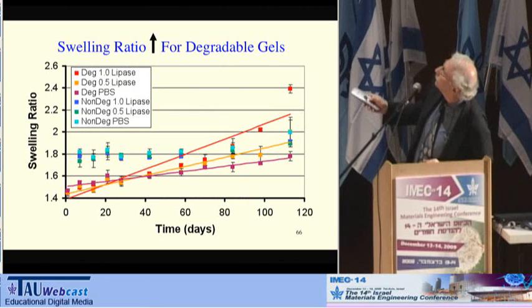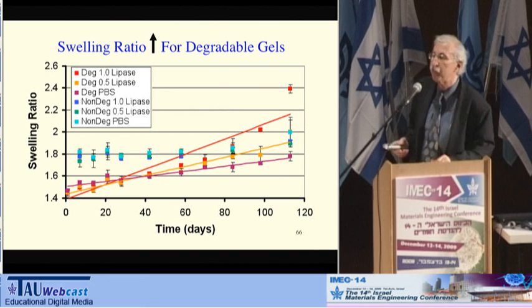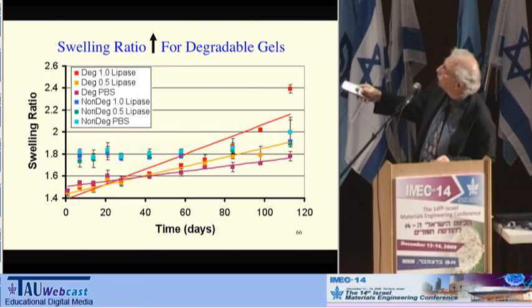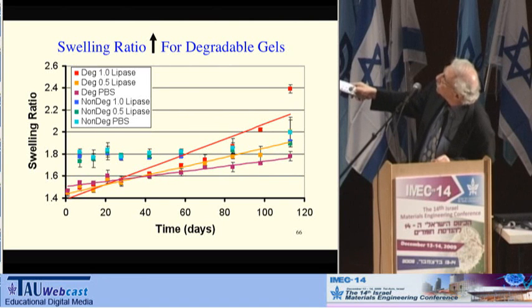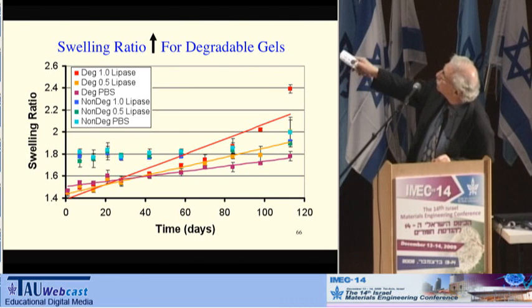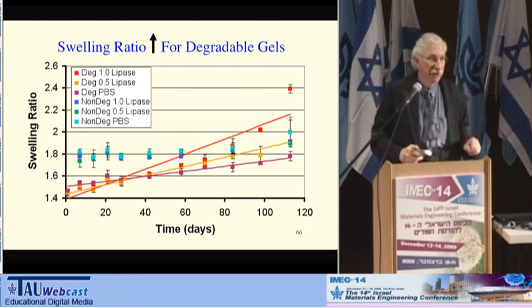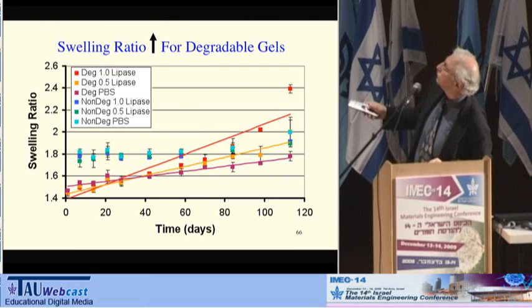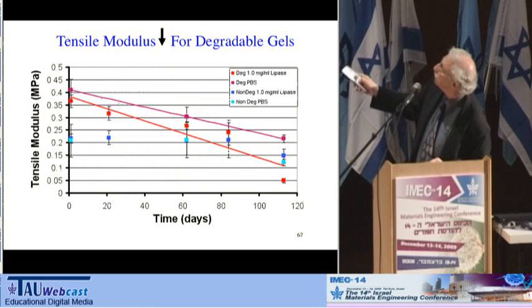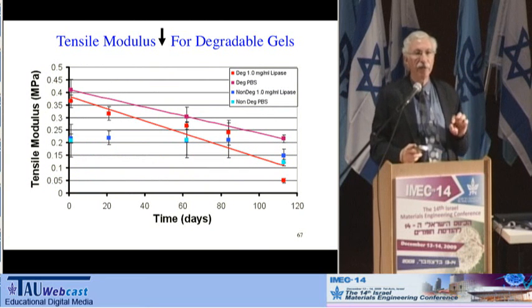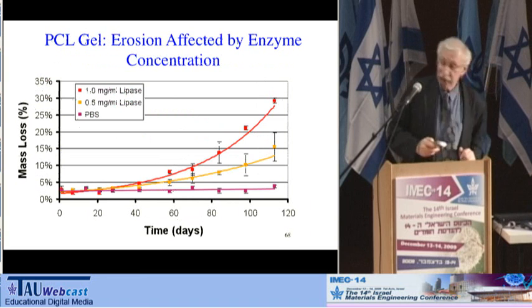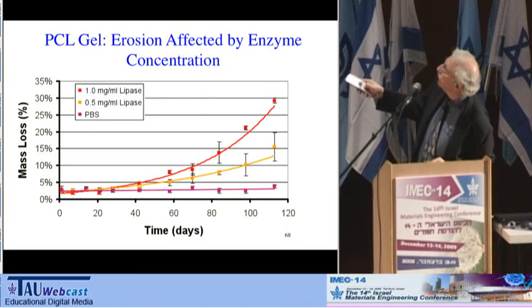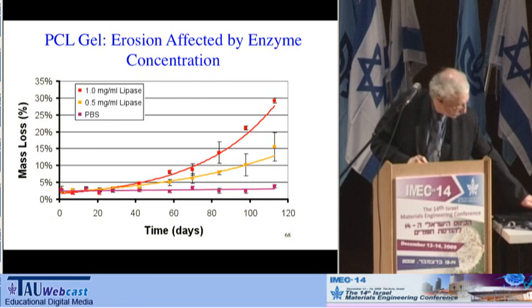So, for example, we can look at the swelling ratio, and we're using a lipase, an esterase, to speed up the degradation. Sure enough, the blue ones are a biostable one, and the red ones are the degradable ones. And sure enough, the higher the concentration of lipase, the more rapid the swelling. In other words, we're breaking down those bonds. Similarly, we can look at the tensile modulus and notice the tensile modulus decreases in a dose-dependent fashion with the amount of lipase. And we can also look at the mass loss, and again see the mass loss increasing with time on these materials.